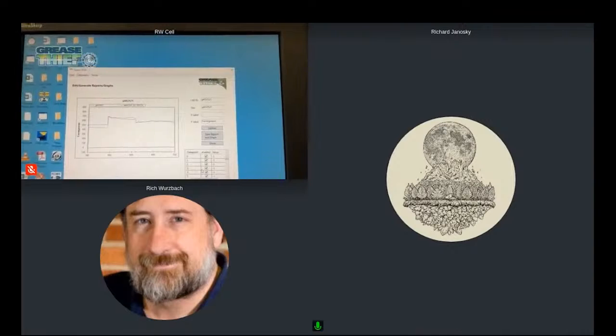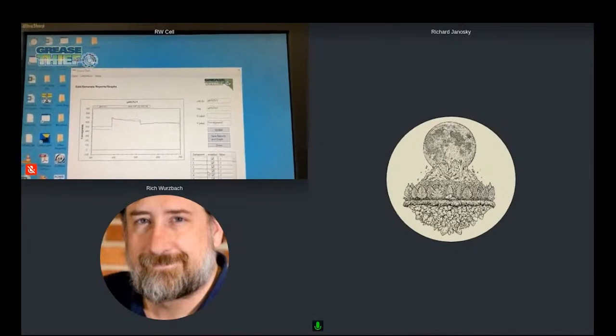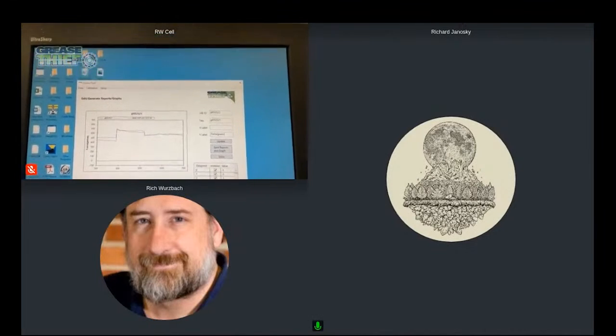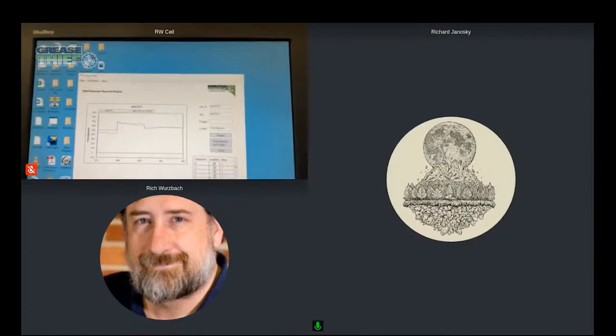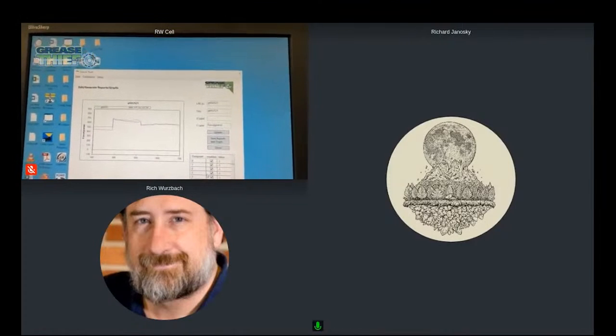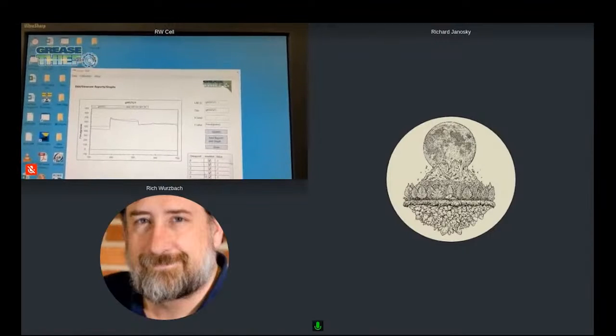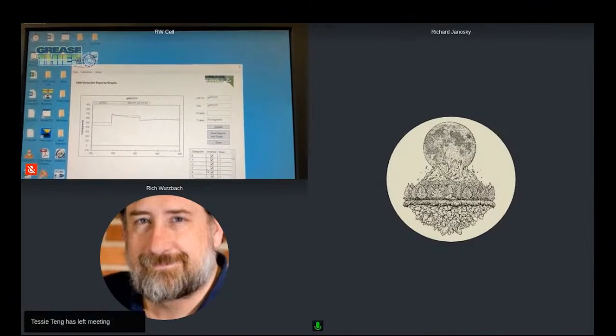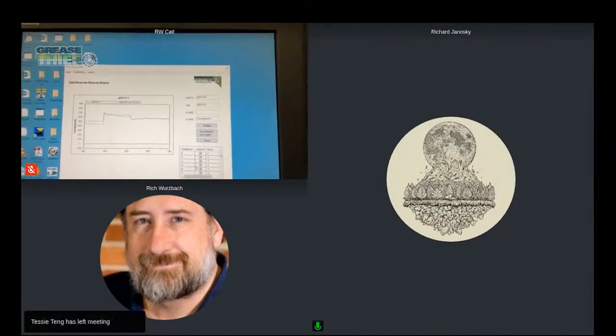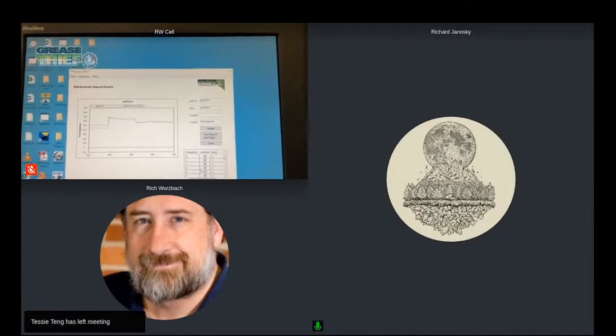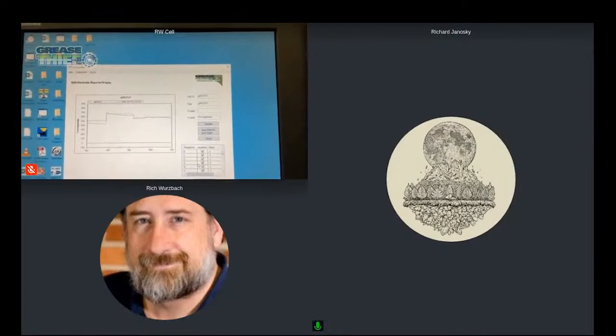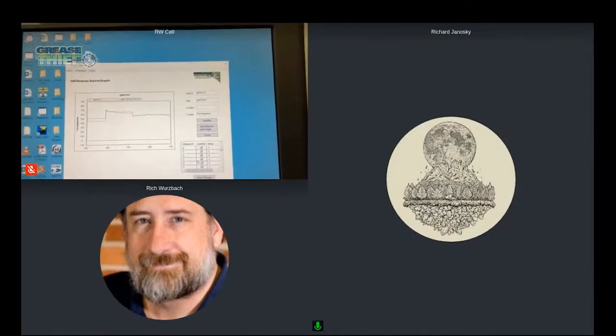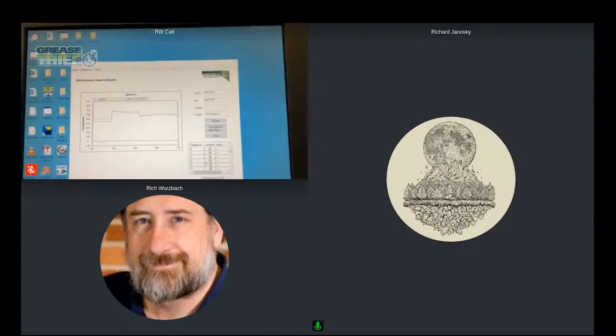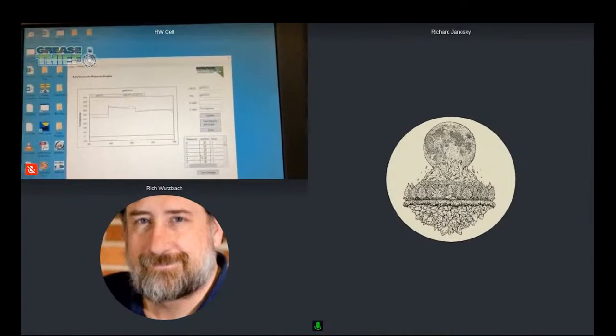Some applications, this is normal and expected. So for example, in a wind turbine, we might be expecting the grease to drop quickly, and you might see a GTI of 60 to 70 right away because the grease is getting beat up, but then it will hold that level, and that's kind of normal. So that's also the important thing, like oil analysis, is establishing a trend to understand what is normal for that application, because not every application is the same.